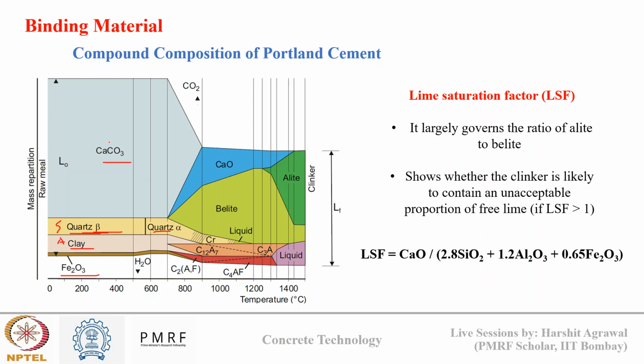Beyond 600 we'll see that calcium carbonate will liberate CO2 and convert into CaO. Subsequently belite and certain calcium aluminate phases will also start to form. Beyond 1200 degrees Celsius, you can see this belite phase, C2S, starts to convert into alite. And CaO starts to blend with the quartz and clay to form belite. So these phase conversions start to happen.